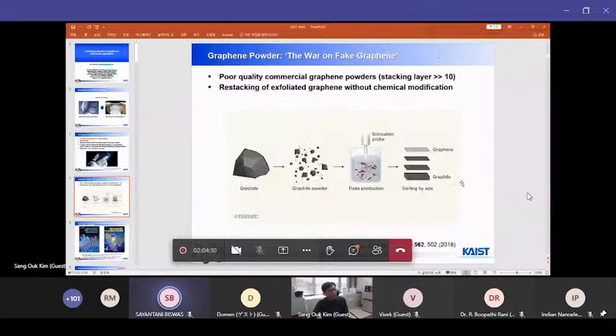So in the current stage, the commercialization of graphene is much more focused on powder type graphene rather than large area graphene CVD synthesis. But there are quite many graphene producers worldwide, right? About 5 years ago, there was one article published in Nature entitled "The War on Fake Graphene." Actually, several scientists tried to analyze most of the well-known commercially available graphene powders, and based on their careful examination, they could find that most of the commercially available graphene powders have a very high stacking number, much higher than the value of 10. Actually, 10 is the ISO standard to define graphene material.